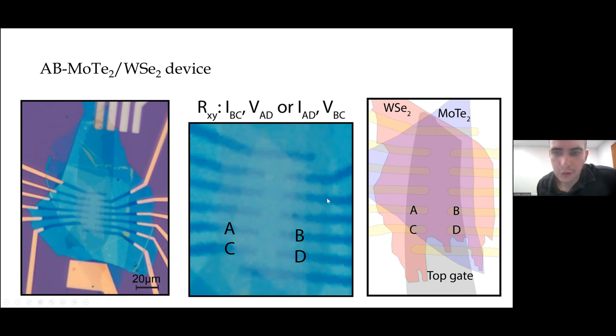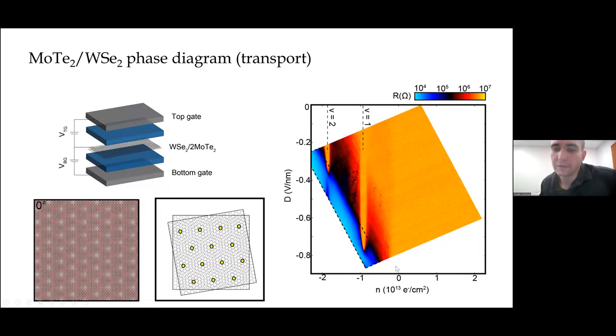So I'm showing you two-terminal transport as a function of electron density and displacement field. You can see that for one sign of doping, we don't see any conductance at all. That's probably not because the system is totally insulating. It's probably more a property of the contact. So these TMD systems are notoriously difficult to contact.